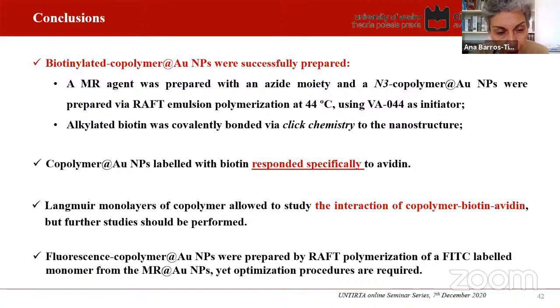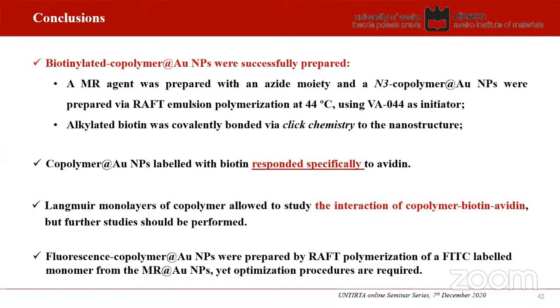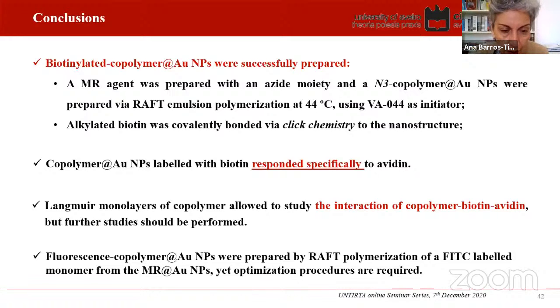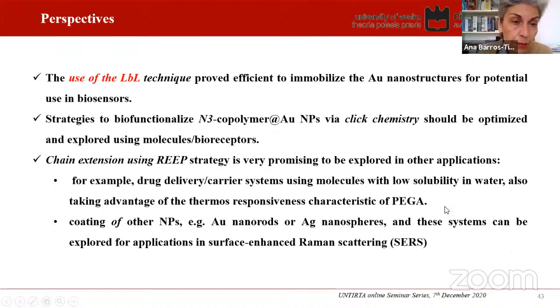As regards the fluorescent copolymer gold nanoparticles prepared via RAFT, the FITC labeled monomer from the macro-RAFT was obtained, but this procedure still needs optimization, especially if we want to combine the anchoring of the fluorophore with the biosensor.